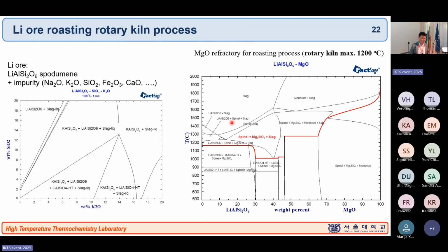So this is another one, the lithium ore rotary kiln process. A lot of people, especially if you want to make a lithium battery, we have to extract the lithium; we have to have pure lithium, lithium hydroxide or lithium carbonate as a starting material. And they typically produce it from ore, like spodumene ore, or from brine, LiCl, which is liquid. So this is the spodumene ore process. They want to transform the structure from alpha, beta, gamma. There are three phase transitions, and naturally the ore crystal structure is too dense, so you cannot make a chemical reaction to extract out the lithium. So that's why they want to transform this material from the very dense one to the less dense one for accelerating the extraction process. So they are using this rotary kiln at around 1200 degrees Celsius for acceleration of this phase transformation.